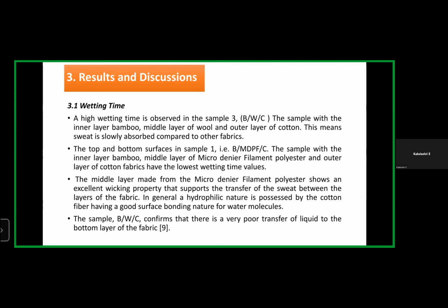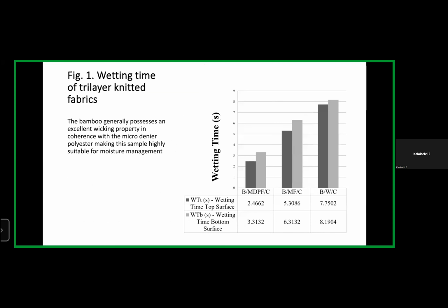In general, the hydrophilic nature means materials with special affinity for water, that means maximizing contact with the fabric. The microdenier polyester hydrophilic nature is possessed by the cotton fiber, having a good surface bonding nature for water molecules. Sample 3, bamboo wool cotton, confirms that there is very poor transfer of liquid to the bottom layer of the fabric. These are the results. You could see the wetting time is less for sample 1 and higher for sample 3. That means a good wicking moisture property for sample 1 and poor for the bamboo wool cotton sample.